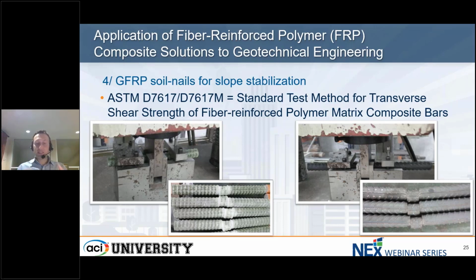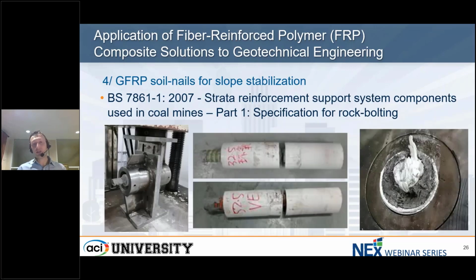So you will see that when you test FRP bar compared to steel in this condition, we get fundamentally different results because there's no surrounding material. Again, this is the pure dowel effect. However, there's a very interesting BS standard, 7861, as you can see here on screen, that is originally meant for coal mines. So this is a pure geotechnical engineering design guide. And what's very interesting is that they do address the specificities of both steel and FRP. That's one of the few exceptions I was mentioning earlier, because geotechnical engineering generally only considers steel.